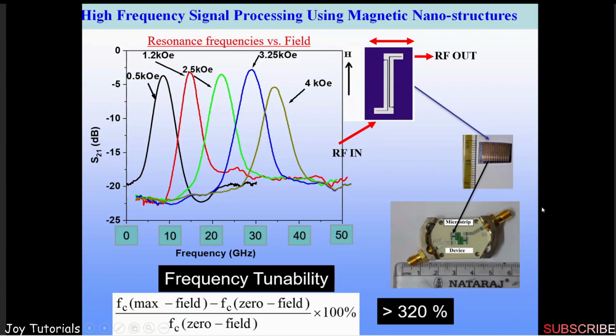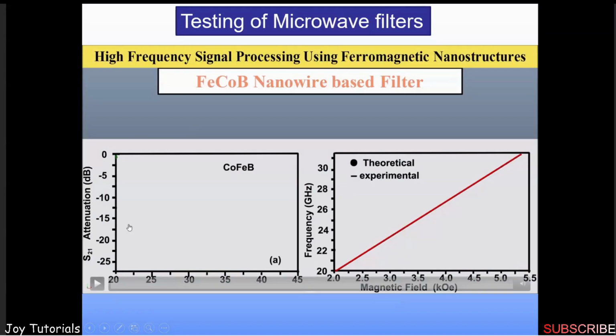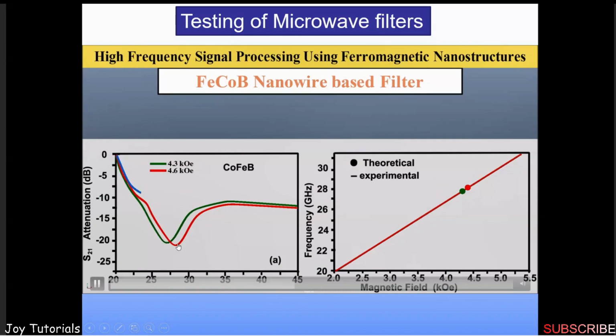So we design other kinds of devices which are electric voltage devices. As I said, these are voltage devices, meaning these can be multiferroic, with the multiple characteristics of ferromagnetic and ferroelectric. So one can tune the device by using a voltage rather than a magnetic field. What we saw here are the iron cobalt boron nanowire-based filters. This is the filter characteristic. There is a low field. Then if you increase the field, you can have a stop band starting from something like 28 gigahertz going towards 30 or 32 gigahertz. So this is one of the nanowire-based filters.